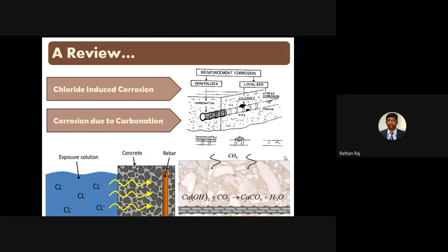So carbonation corrosion will occur maybe after 10 years or after 20 years, and it will not start immediately, particularly if we are using high performance concrete or high strength concrete or very dense concrete. Years together it will take. After that only, due to some deterioration of the concrete and its porous structure, this corrosion takes place. So due to carbonation, it will reach and affect the passive layer on the steel. So first we have to know what carbonation actually is.